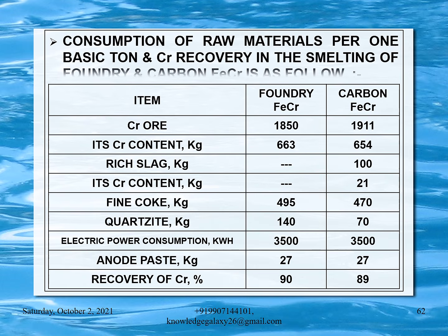My dear friends, this table shows the consumption of raw materials per 1 basic ton and chromium recovery in the smelting of foundry and carbon ferrochrome as follows. Chrome ore: foundry ferrochrome requires 1850 kg, carbon ferrochrome requires 1911 kg. Its chromium content is 663 kg for foundry ferrochrome, and for carbon ferrochrome it's 654 kg.